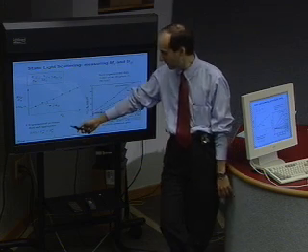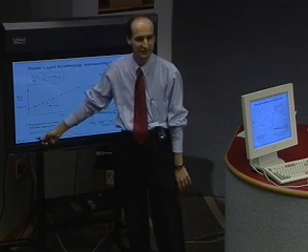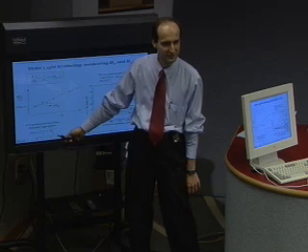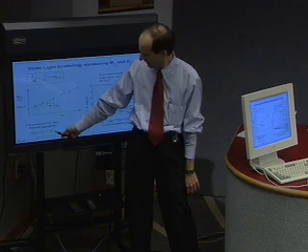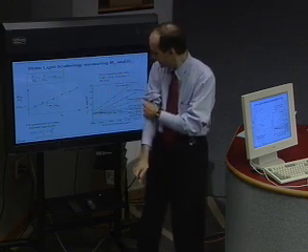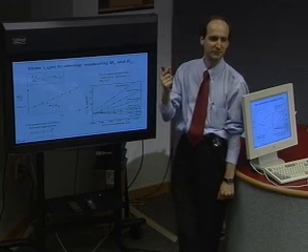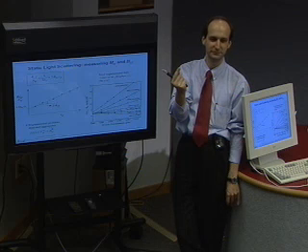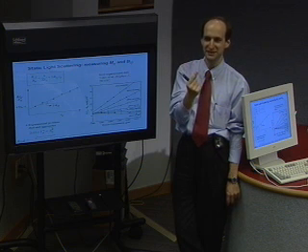Luckily they did. Now the problem with proteins is dust and aggregates. They scatter so much that just a single dust particle, which is, let's say, 10 times bigger than the protein, is going to scatter 10 to the 6th power, 1 million times more than the protein molecule. So a single dust particle scatters as much as 1 million protein molecules. And you don't want to have this single dust particle inside there, because then the data is going to be complete junk.